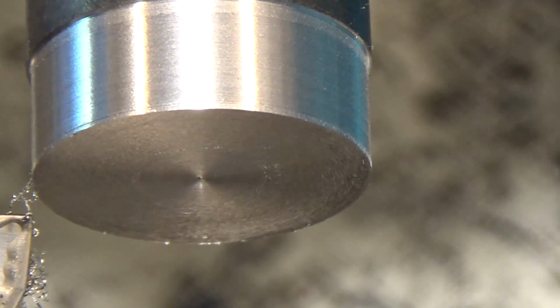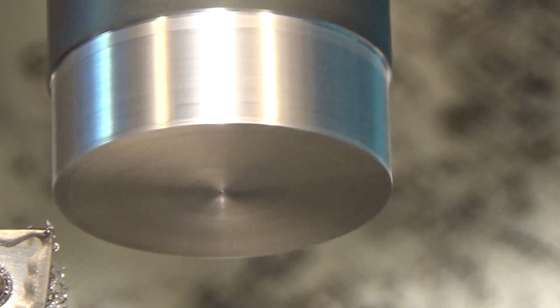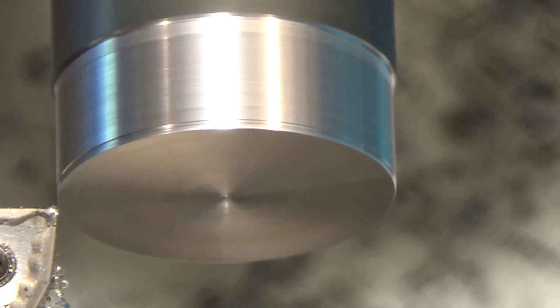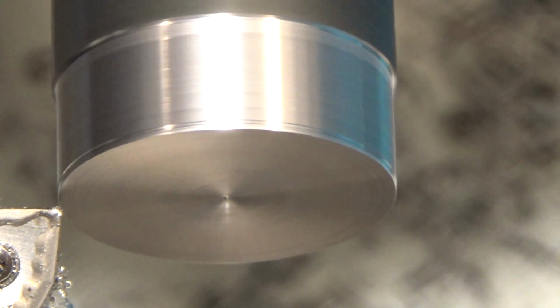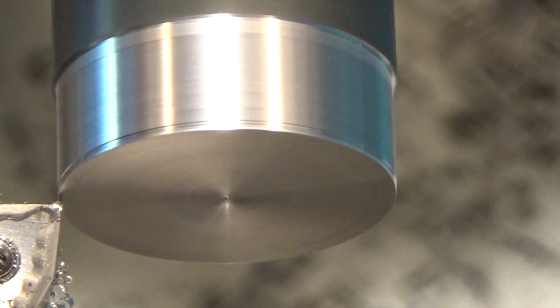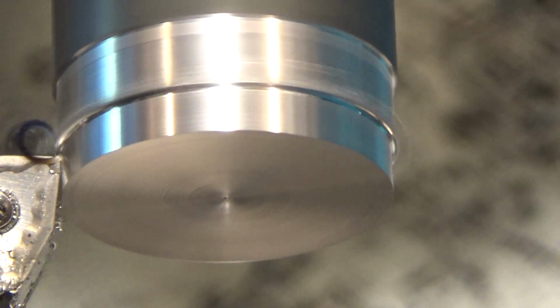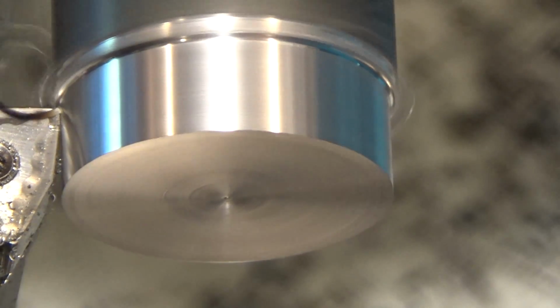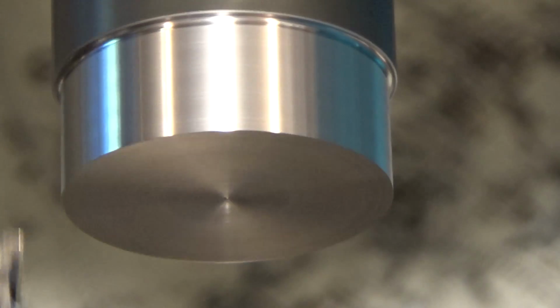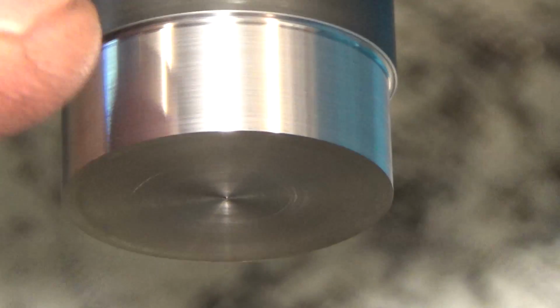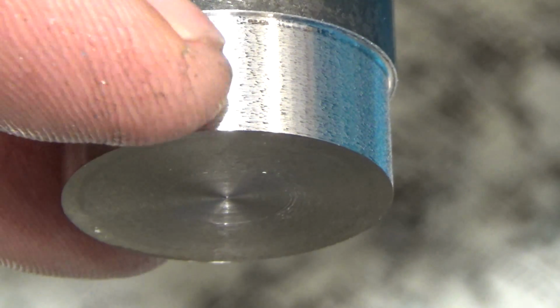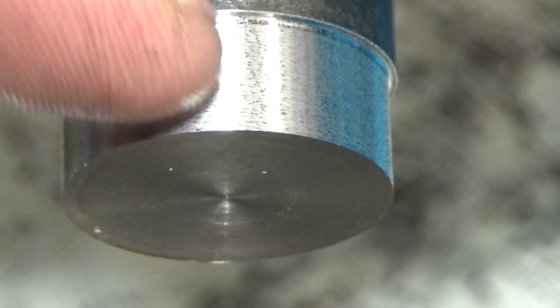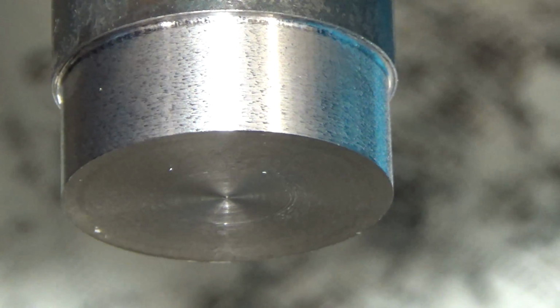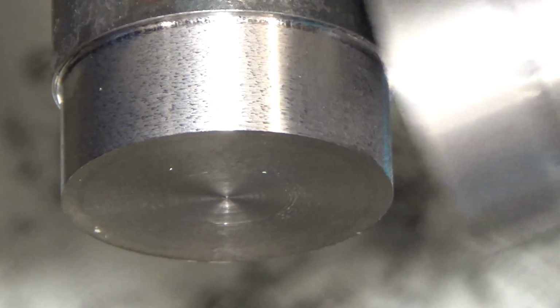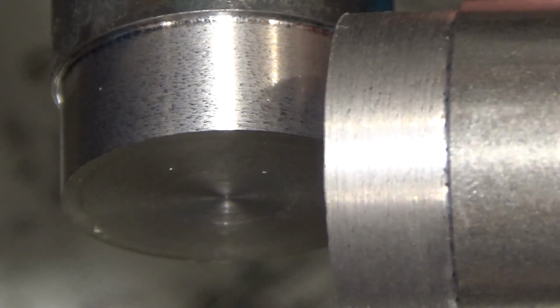So we're continuing with the tempered stock. We're going back to high speed at 1120 RPM, about 25 thousandths depth of cut again. Blue turnings coming off of it. Chip breaker's not engaging. Finish already looks superb by comparison. And it is. There's a little bit of surface tearing, but you can't feel it with your fingernail anymore. Still shiny, and again here is the plain annealed for comparison. So there's a much better finish, a little bit of really fine-grained sandpaper, and you're good to go.